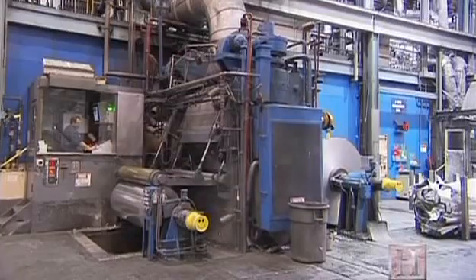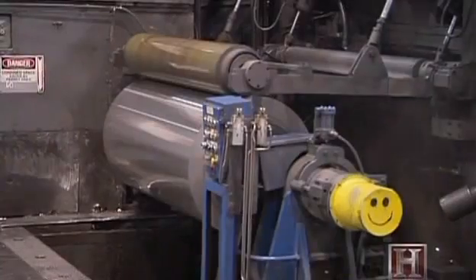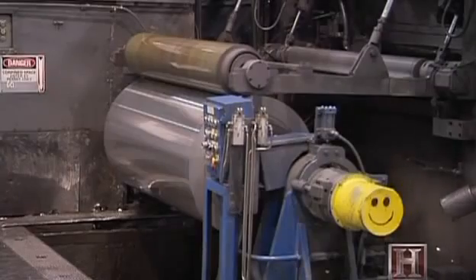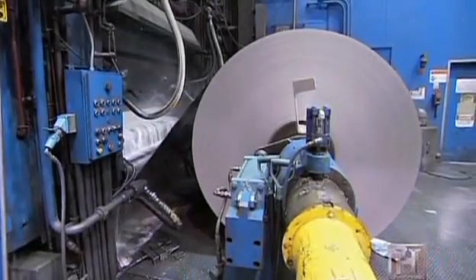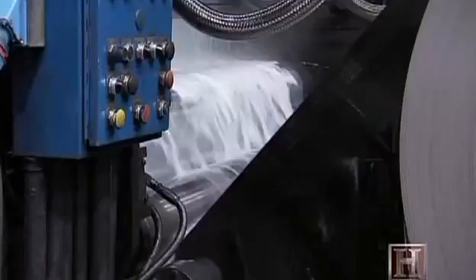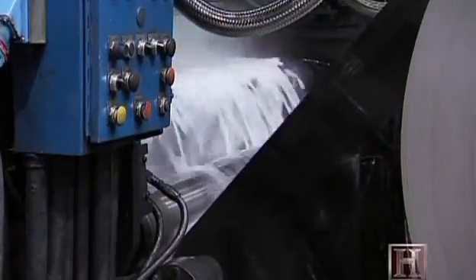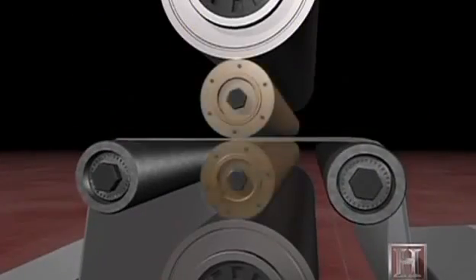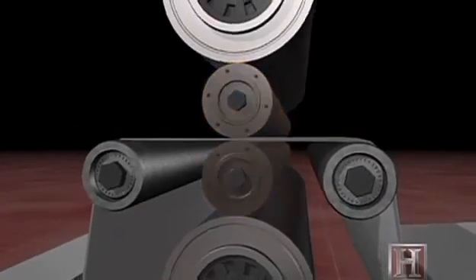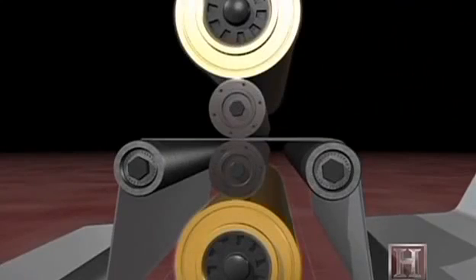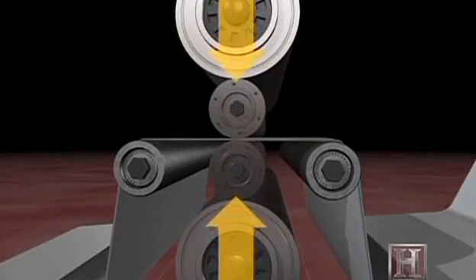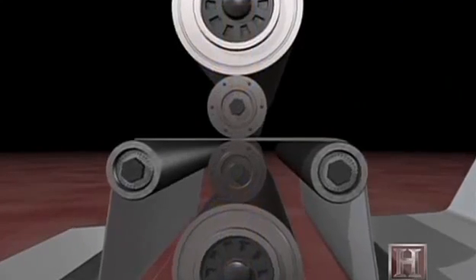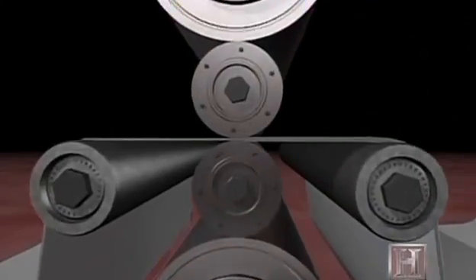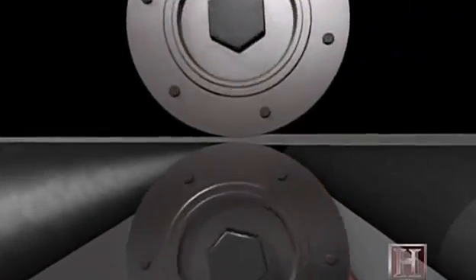Thinning the softened sheet is a job for the rolling mills, since the pressure they exert on the aluminum could create sparks and ignite fires. A cooling lubricant douses the sheet as it enters. Inside the mill, the sheet passes between a pair of powered spinning rollers. Larger, non-powered rollers positioned above and below them apply even pressure, helping them flatten the sheet in a uniform manner. One pass through the mill reduces the sheet thickness by half.